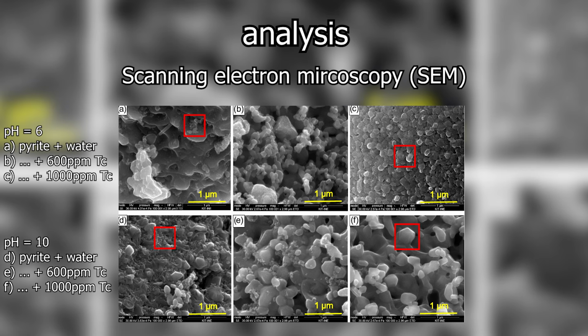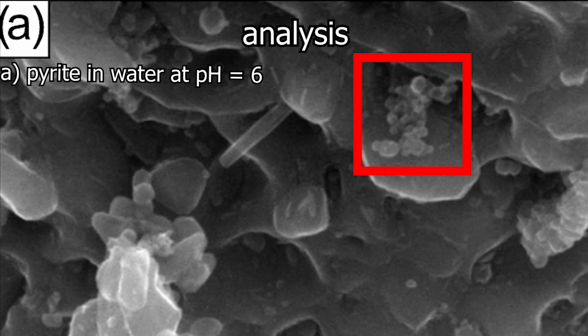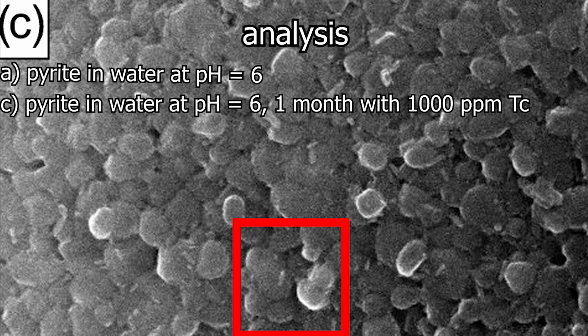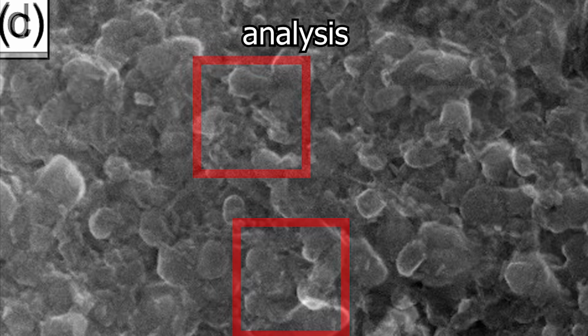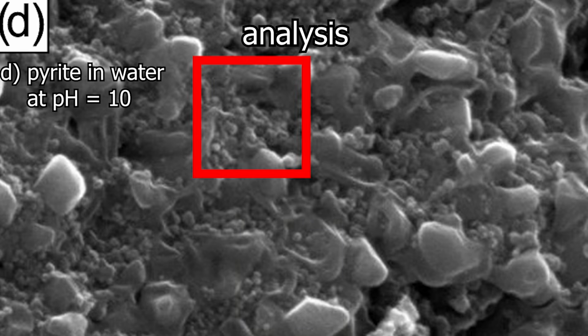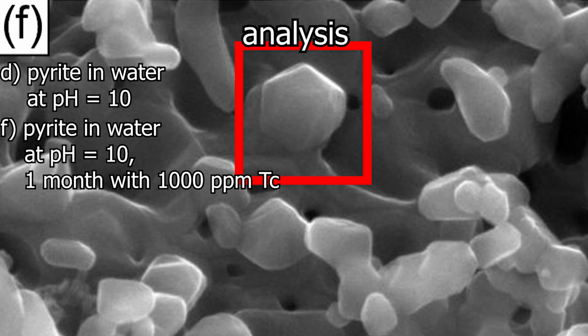There are two ways in which the technetium is structurally immobilized by the pyrite. So now let's take a look at this iron 3+. This is present in mineral form as an oxide. When the sorption experiments are carried out at a pH value of below 7.5, hematite is formed, and above a pH value of 7.5, magnetite forms as an iron 3+ containing mineral on the surface of the pyrite, which has interacted redox actively with the pertechnetate ion.